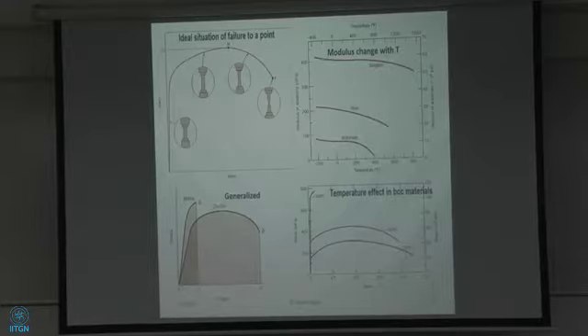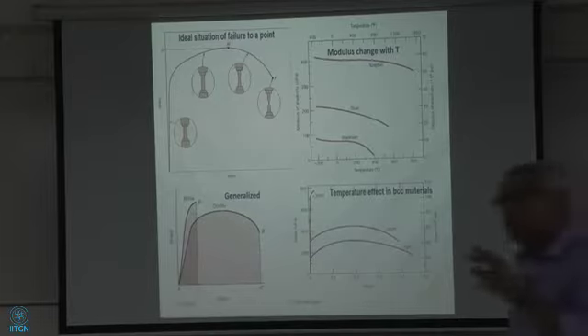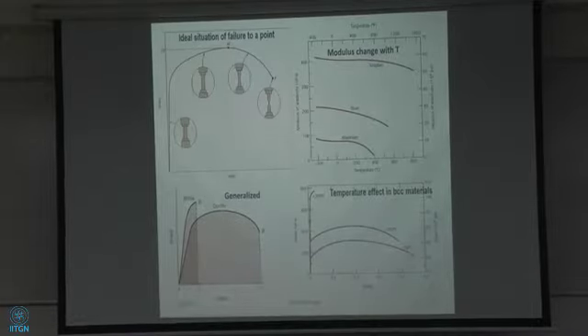Modulus change with temperature. Elastic modulus really doesn't change that easily. It's one of the most difficult things to change. There's a good change with temperature, but if you want to do alloying and change the modulus, you're not going to change much, except in aluminum lithium alloys. The springs, if you consider it as two atoms and there's a spring in between, the stiffness would fall down. So as the temperature is decreasing, the spring is getting tighter.